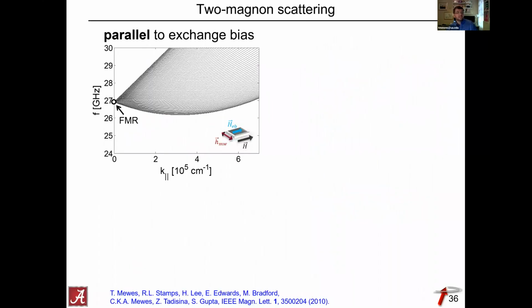Well, if it's caused by two magnon scattering, that shouldn't be too surprising, because if we look at the dispersion relation of the spin wave in an exchange biased system, we actually get a dispersion relation that looks something like this, where you have the FMR mode and you have all these degenerate spin waves here. And these are the spin waves that the FMR mode can scatter into. And what needs to happen for that is you need roughness at the interface. So you actually have a scattering potential, so you can actually scatter into those spin waves.